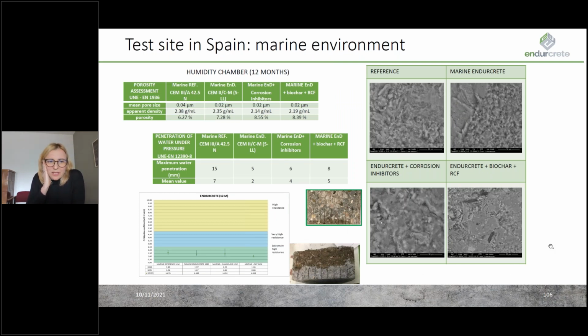So additionally, we can here see the results of the porosity and density and mean pore size. Most important is that both concretes performed really very well. Also, the water penetration was much lower compared to the reference concrete. In the SEM scans, we can see that no significant difference in the microstructure, and the overall impression is that EnDurCrete concrete had very low permeability.